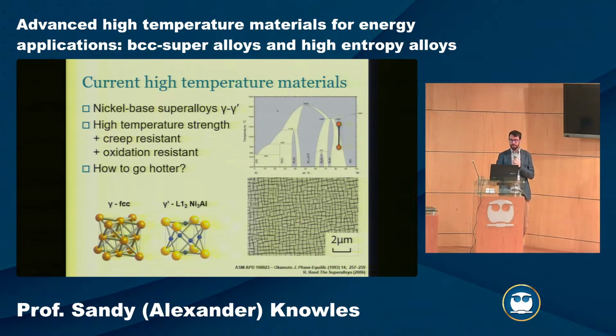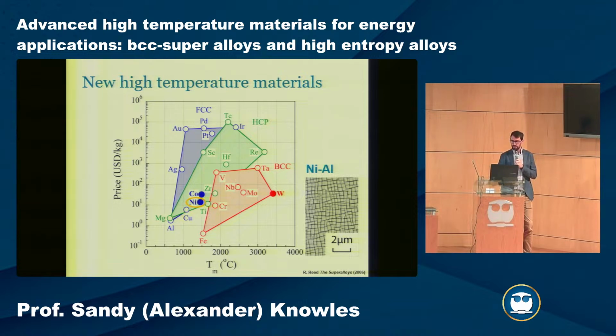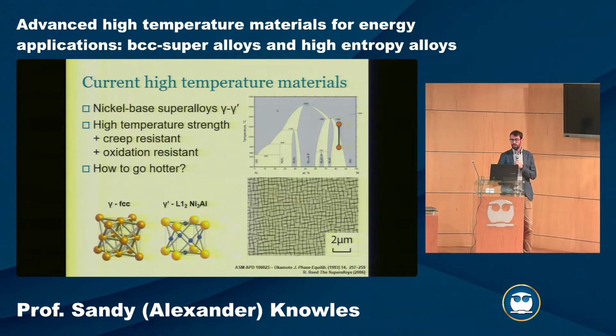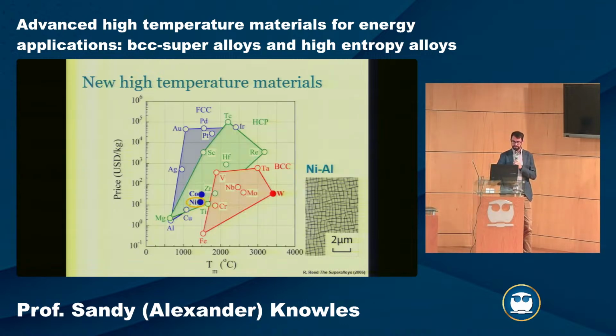And we can produce this by understanding the phase diagram. So the phase diagrams are the mixture of elements. As we add nickel and aluminium together, the regions in purple are the different phases that form. So we have the FCC nickel on one side, and then we have this nickel-3 aluminium intermetallic phase. And if we choose appropriate temperatures and compositions, we can go from a single phase FCC and we can precipitate this nickel-3 aluminium phase. And this is something that we want to exploit in our own alloys.